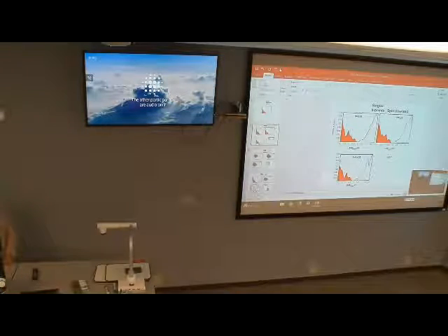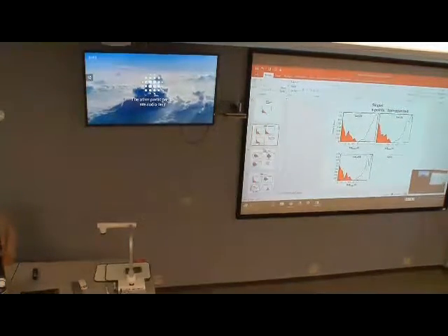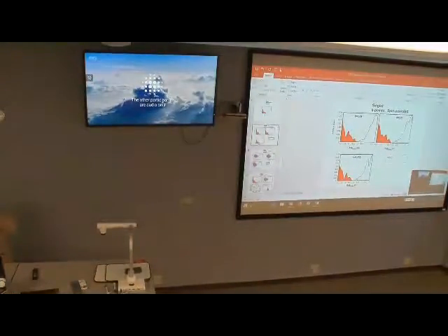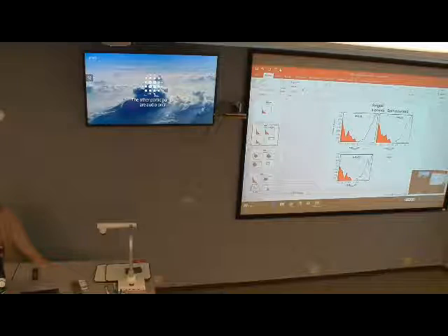Answering your question, the dispersion curve is not flat. If one zooms in on this figure and looks at the gap, I see that. So it's evidence that it is not flat, and taking dispersion into account is not a stupid idea. Is it worth the pain and suffering of k points? Probably. So, returning to your closed gap, technically the electronic structure in this case probably makes not much physical sense.